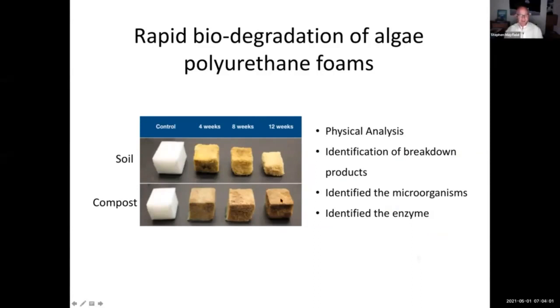We now actually have better compost. We can degrade the compost ones faster than that. So this is home compost, not industrial composting. Importantly, while we were doing that, we were doing a physical analysis of the breakdown of the foam. We were identifying the breakdown products to make sure that we weren't producing toxins. We weren't predicted to. We know where the bonds are. We know what comes out of them when we break them. Sure enough, no toxins. But importantly, we identified the microorganisms and the enzymes.